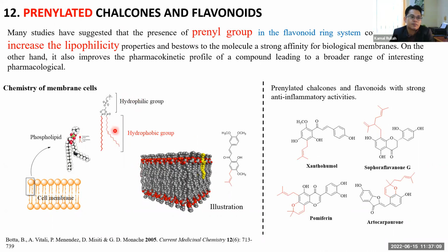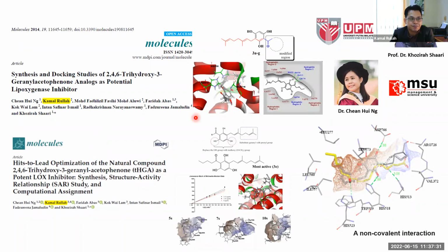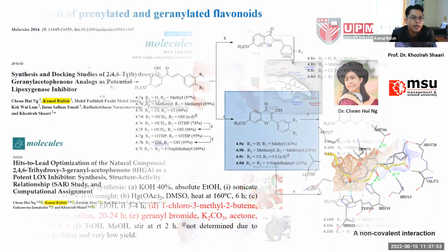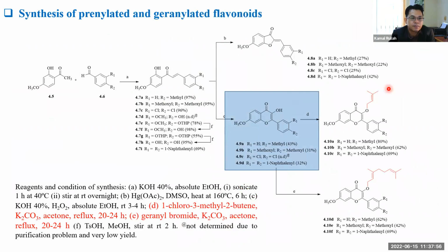Here, in the concept, they have a hydrophobic nature. The cell membrane belongs more to the hydrophobic group, so this can give us more active compounds if we apply it to our compounds. And alhamdulillah, we have succeeded. This is a sample. The concept was proven by our collaborative research with UPM, with Prof. Khozirah and Dr. Chean. We succeeded in identifying the prenyl group in the LOX substrate binding site. This inspires us to apply prenyl groups to our flavonoid compounds. And here we succeeded in inserting the prenyl group into our compound.